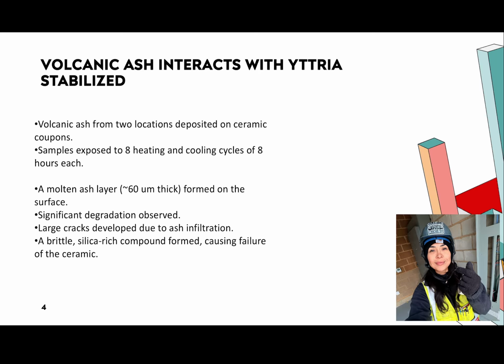condition. Researchers collected volcanic ash samples from 2 different locations and deposited them onto the surface of the 7YSZ ceramic coupons, which is the yttria stabilized zirconia. These samples underwent 8 rigorous heating and cooling cycles. What came of those cycles is a thick layer of molten ash formed on the ceramic surface. The melted ash aggressively infiltrated the fine grained microstructure of the ceramic, and the overall effect was a complete failure of the material, characterized by the development and propagation of large cracks throughout the substrate.